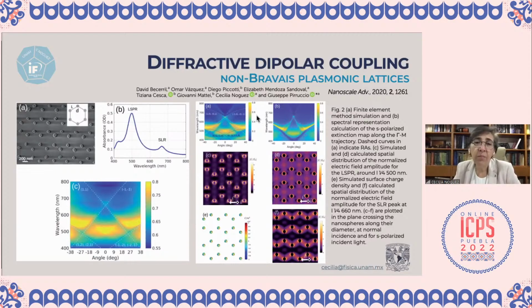Another important thing that we can do is, for example, we can have this kind of arrays. These are actual arrays with a hexagonal composition of nanoparticles. We can couple the plasmonic response of the system between nanoparticles, and now we can have a propagating mode. These are the experimental measurements of these modes, and we can look at different kinds of contributions. Here, if you have a constant, this is not a propagating mode. This is the angle with respect to the plane of the system that we are looking at. And also we can have these kinds of modes that are propagating. And you can see here, for a given frequency, that the near field is enhanced along one direction or another one, okay?